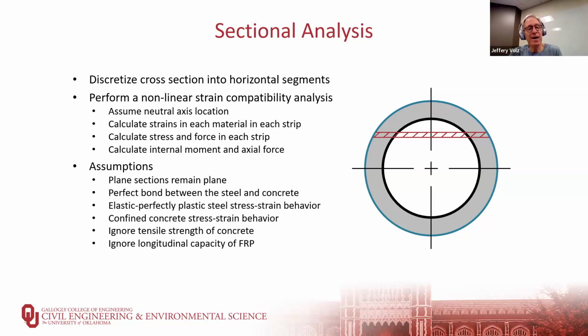We use a stress strain diagram for confined concrete, and there are guidelines on how to convert the stress strain diagram for unconfined concrete to that for the confined concrete based on the degree of confinement that the steel and the FRP provides for the concrete. We typically ignore the tensile strength of the concrete, and we also ignore the longitudinal capacity of the FRP.